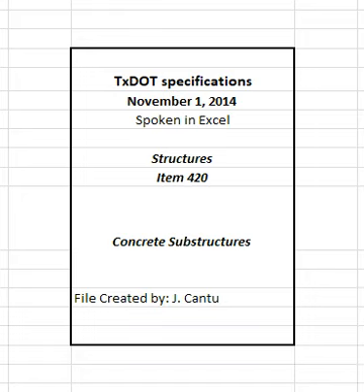Cure all concrete for 4 consecutive days except as allowed for the curing options listed below. Use form or membrane curing for vertical surfaces unless otherwise approved. Use only water curing for horizontal surfaces of HPC or mass concrete. Use water or membrane curing for horizontal or unformed surfaces for all other concrete. Use one of the following curing options for vertical surfaces, unless indicated otherwise.